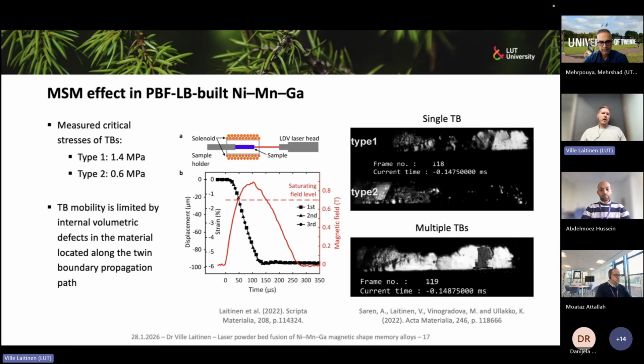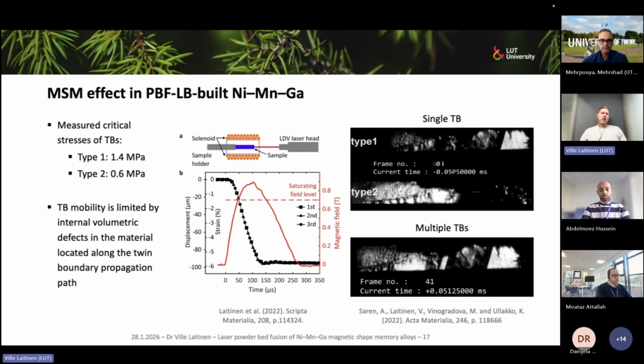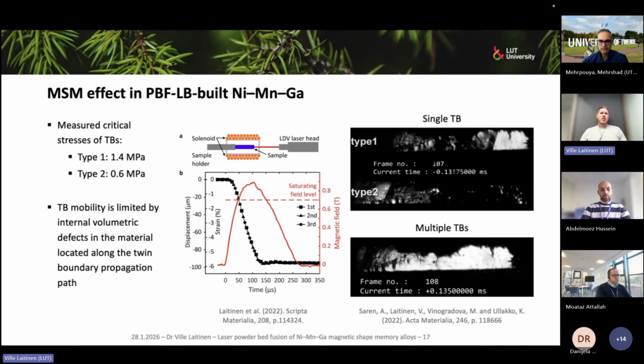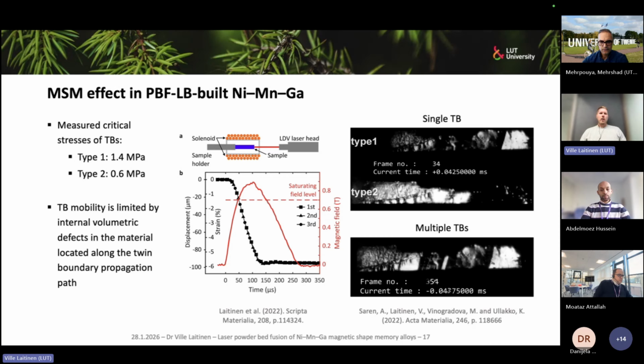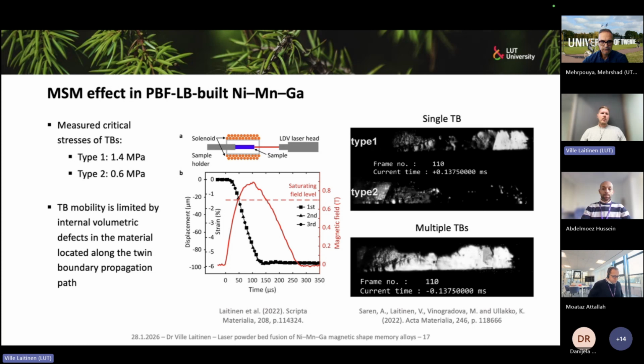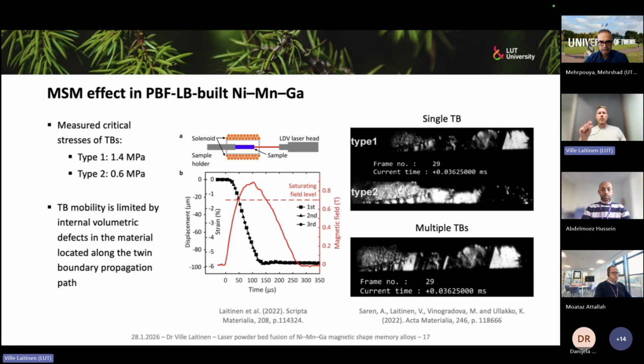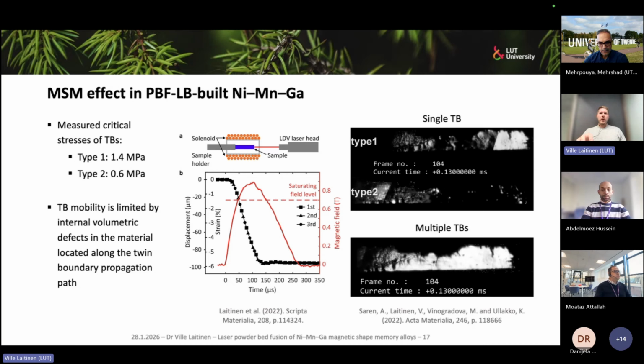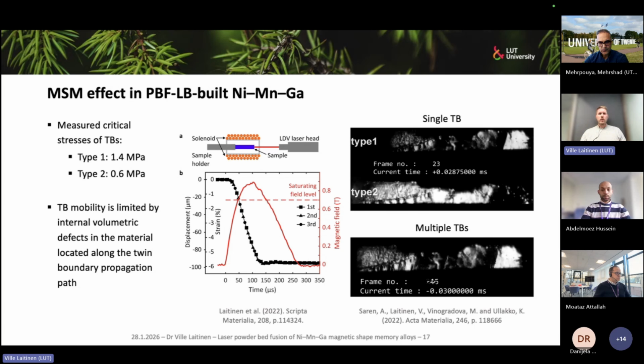But now, if we look at the actual twinning values, we see that the type 1 and type 2 twin boundary mobilities in this material are a little bit lower than what you would expect from a really high quality single crystal. I mentioned type 2 is 0.1, then in a typical single crystal type 1 would be 0.7, 0.8 megapascal. So we are slightly higher, and this is mostly because of internal defects. One key characteristic that we observed in this test was that twin boundary mobility might be limited by some volumetric defects in the material itself. For example, there might be some higher density manganese particulate inside, and it dissipates into the lattice in the heat treatment, and we have a compositionally different zone that has different twinning characteristics.